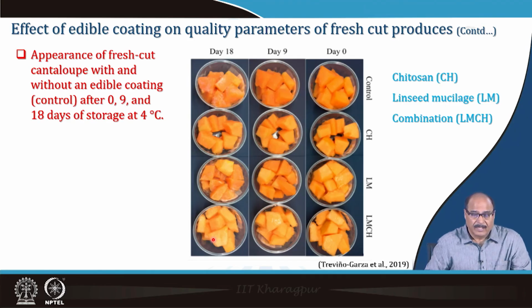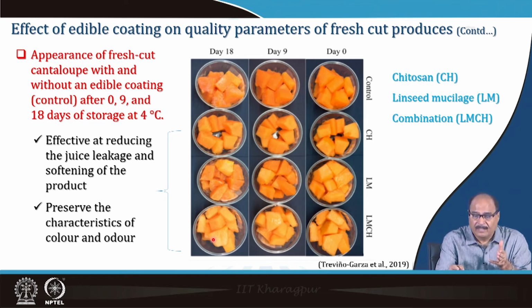So here you can see the effect of coating on the appearance of fresh cut cantaloupe with and without the edible coating, that is after 0, 9 and 18 days of storage at 4 degrees Celsius. The first top 3 is the control sample, then the bottom 3 is the chitosan coating, then the linseed mucilage coating, and the bottom one is the LMCH combination of linseed mucilage and chitosan coating, and it has been found effective in reducing the juice leakage and softening of the product, and it preserves the characteristics of the color and odor, and it is even visible. You can see it has been found very effective, that combination treatment, the color is almost similar to that of the natural fresh one.